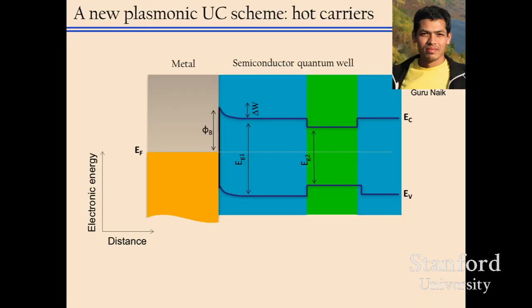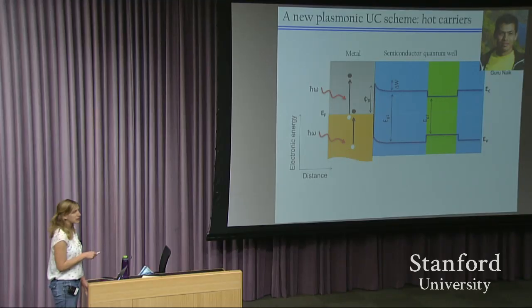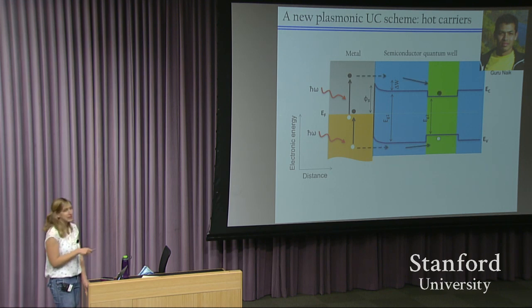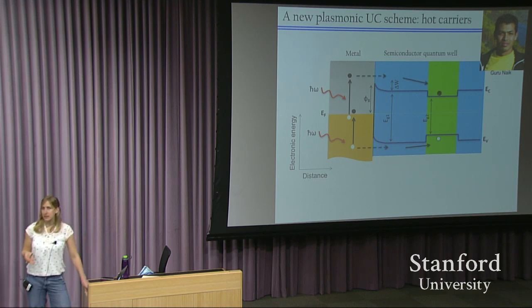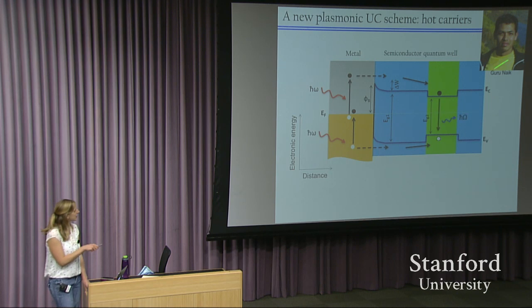We have a nanostructured metal near a semiconducting quantum well. And when two photons come in, they excite electron hole pairs, basically from the Fermi level up to higher in the band diagram, and from deeper in the metal band diagram up to the Fermi level. And then this hot electron and this hot hole can get injected into the semiconducting quantum well and basically get trapped there until they radiatively recombine to emit a photon that's of higher energy than either of the incident photons.